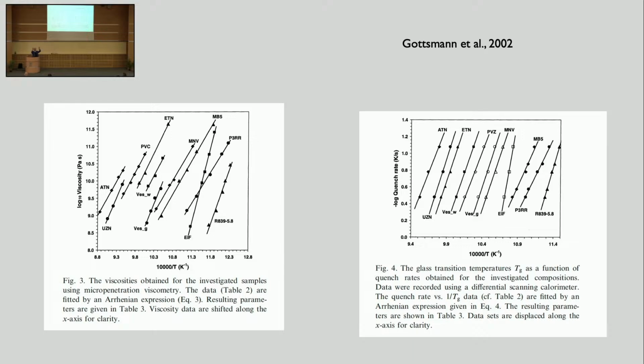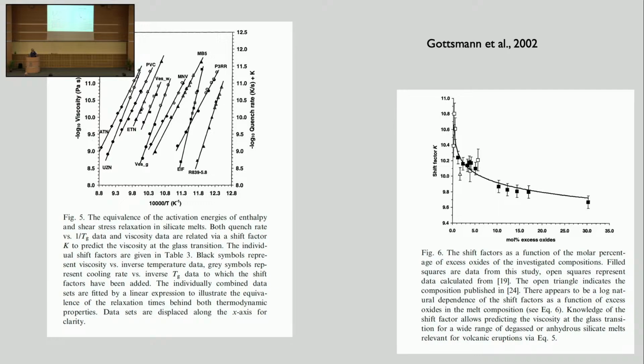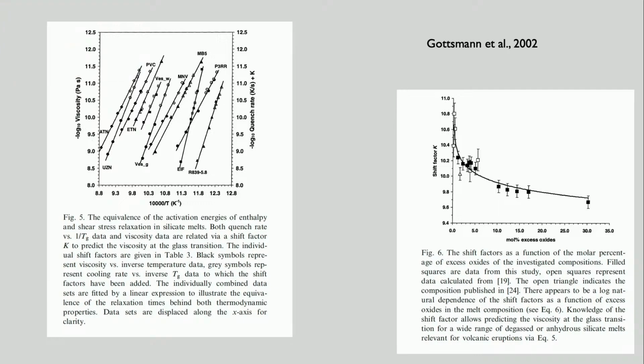It means that you can apply an empirical shift factor, you can do calorimetric measurements, and you can get viscosity data. You can do viscosity measurements, and you can infer calorimetric data, because the whole thing is being controlled by one parameter of the whole system, the relaxation time of the liquid. And on the right-hand side here, you can see that we get a shift factor as a function of composition. It varies a little bit, because these curves are now composite curves. The lines are composed of two different kinds of data. You can see black data points here and white data points, and that's the calorimetric and the viscometric data points shifted by a constant factor, same slope, and that allows us to infer one from the other.